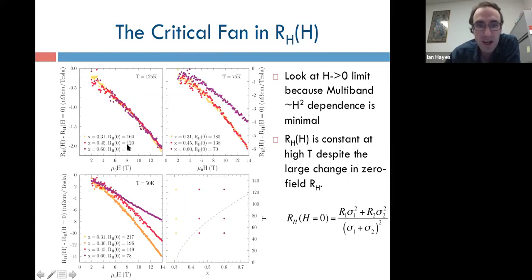Now I just want to back up for a second and point out that this is what you expect to happen just from multiband physics. The conductivities on all these sheets are getting better as you go toward the overdoped side, and so you expect this term to get smaller and smaller, as it in fact does. But if you just compare the field-dependent part, and just look at this decrease of RH with field, that part is exactly the same at high temperature. It's fairly small, but it's resolvable, and the curves lie right on top of each other.